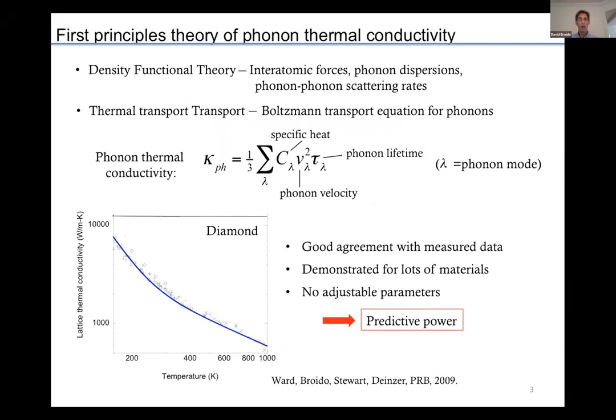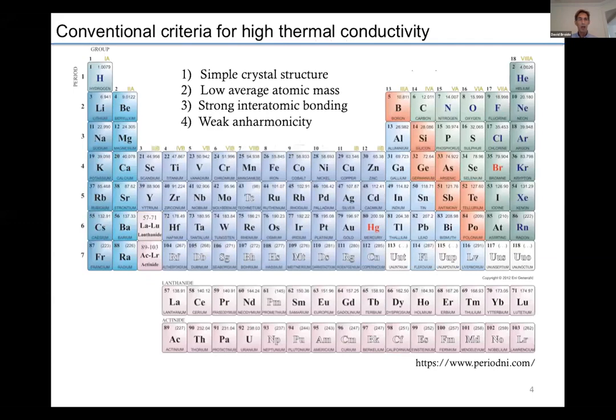And we use a first principles theoretical approach, which I won't have time to describe in detail, but it allows us to extract the ingredients necessary to calculate the thermal conductivity, like phonon lifetimes and phonon velocities. An example of our early work is shown in the plot, which gives the calculated and measured thermal conductivities for diamond. And you can see that there's very good agreement between the theory and experiment. And that's now been shown for lots of materials by lots of different groups, that we consistently get good agreement when comparing the theory to experiment. The theory has no adjustable parameters, and so that means that it has predictive power. So we can look at materials where maybe the thermal conductivity hasn't been measured and make some predictions about what those values should be.